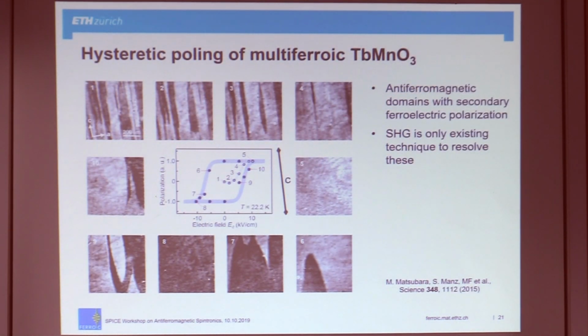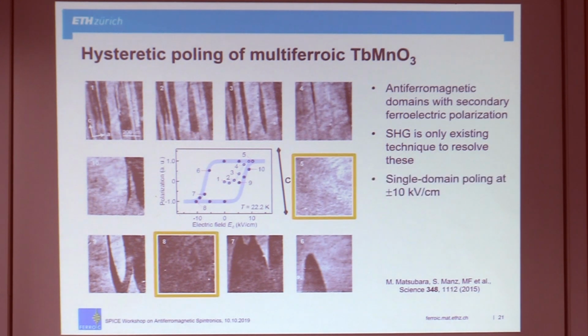So what we then did is we imaged this compound at low temperature and found, yes, indeed, we can see different antiferromagnetic domain states. We coupled to them via this symmetry breaking. So we see the magnetism and the polarization at the same time because they are one-to-one coupled. Via this small, parasitic polarization, we can polarize our material in an electric field. So we can move it through an antiferromagnetic hysteresis by acting on the small polarization. You see how these domain structures shift in the field. In particular, you can get it into one or the other single domain state, which is otherwise very difficult. But here, the electric field helps us to do that.